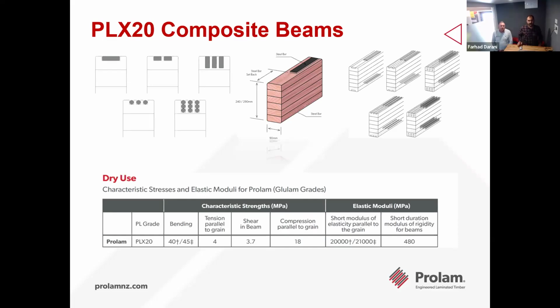And we were aiming to have something which actually offers suitable strength and stiffness as well. So for example, here we can see that we have a bending stress of 40 MPa and 45 MPa for two different products, one being 240 by 90 and the other one is 290 by 90. And then we have also an increased modulus of elasticity as well, which is 20 and 21 GPa.